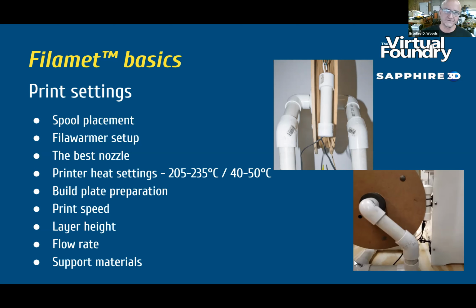It dries it a little bit, and PLA can be annealed somewhat, so it actually causes the material to become stronger. So the setup that we recommend is to hang the spool directly above the 3D printer, about 12 to 18 inches above it, with the Filawarmer nearly in contact with the spool, at an angle that's tangent to the center of the spool. From there, you want enough distance between the Filawarmer and the 3D printer that when the head moves, it's not pulling dramatically. You want a longer sweep and a more gentle angle on the material as it's coming out of it.